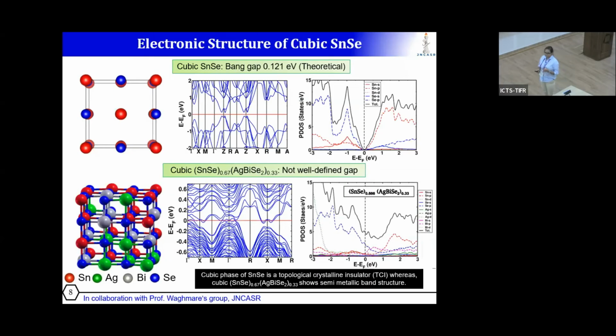Next, to get further insights about the structure and what things are happening, we have done DFT calculations in collaboration with Professor Waghmare's group at JNCASR, and it has been shown that the pristine cubic SnSe is a semiconductor and has a theoretical band gap of 0.12 electron volt.